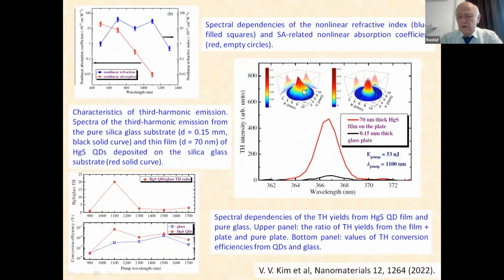Our analysis of third harmonic generation showed the spatial distribution of the third harmonic signal in the case of 70 nanometer thick mercury sulfide thin films placed on the glass plate. We have shown that from the pure glass plate, which has a much greater thickness, around 0.15 millimeter, we also have a very small signal. While for the 70 nanometer thick film, we have a much stronger one, and overall the ratio between those signals becomes a few orders stronger in the case of those films compared to the glass.